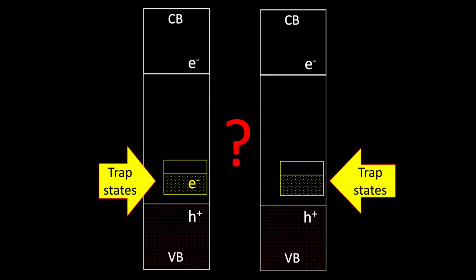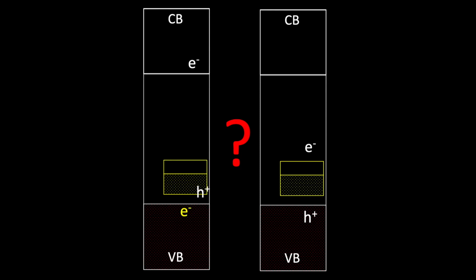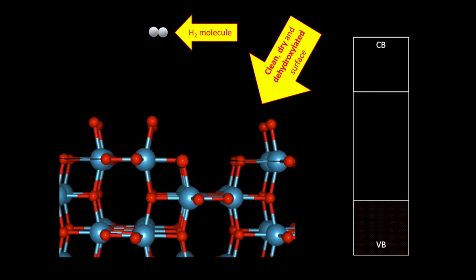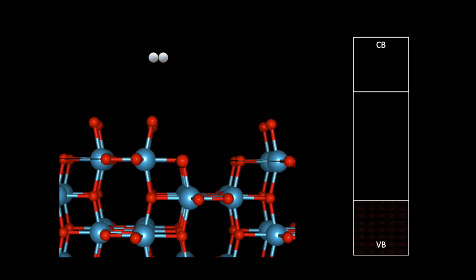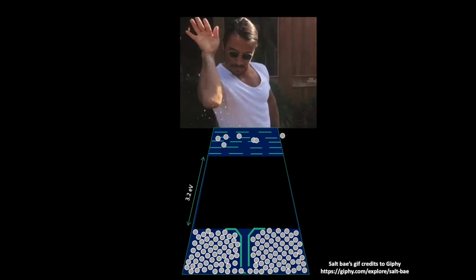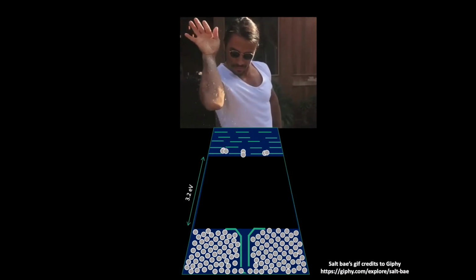In this work, we use a unique approach to confirm presence of electron traps without the need for distinguishing between hole or electron entrapment. Hydrogen dissociation on a clean, dry, and dehydroxylated surface produces electrons. These electrons would populate the lowest empty electronic states either in the conduction band or in any mid-gap states. In addition to electrons, water and oxygen vacancies are byproducts of this reaction. This is like we are adding extra balls to the upper part of our pinball machine.